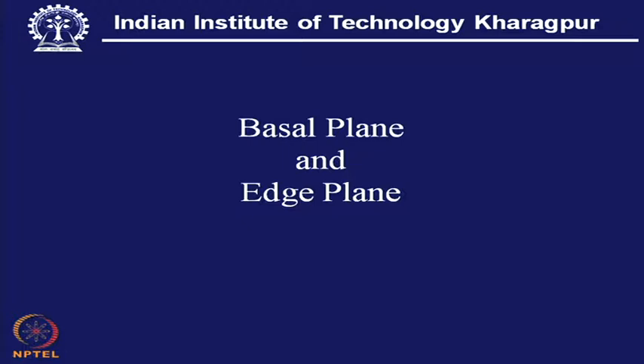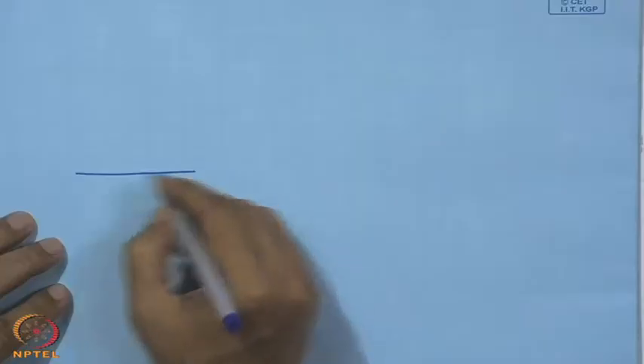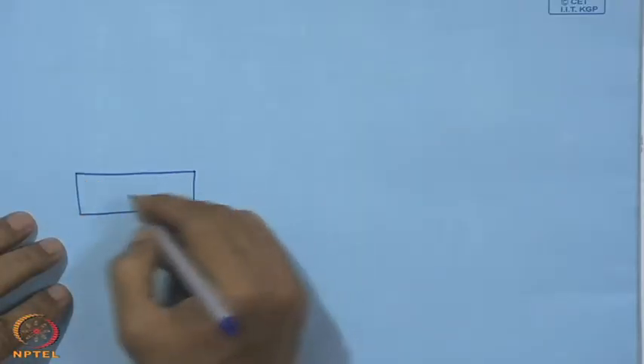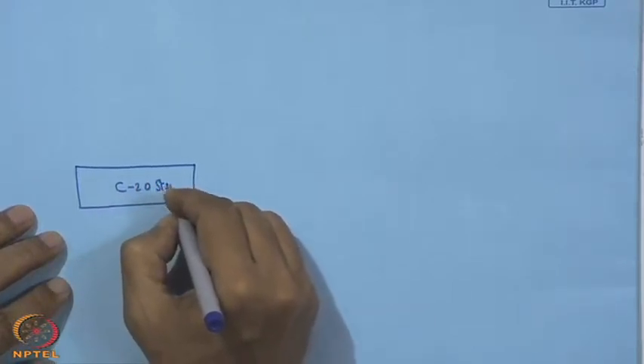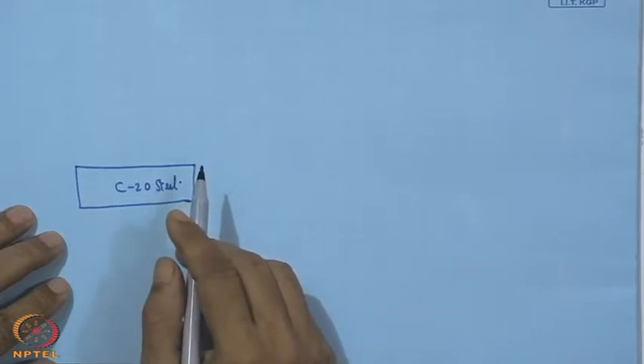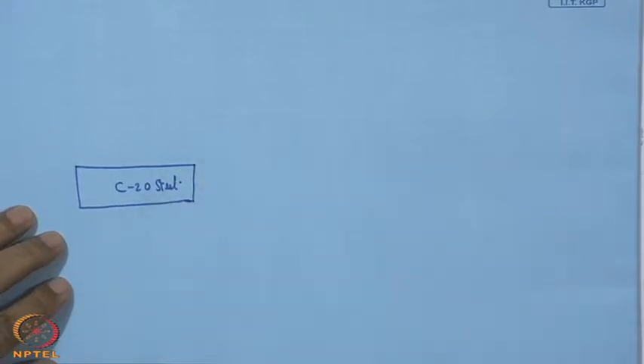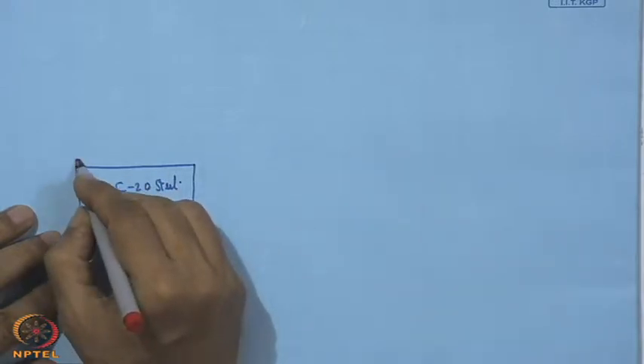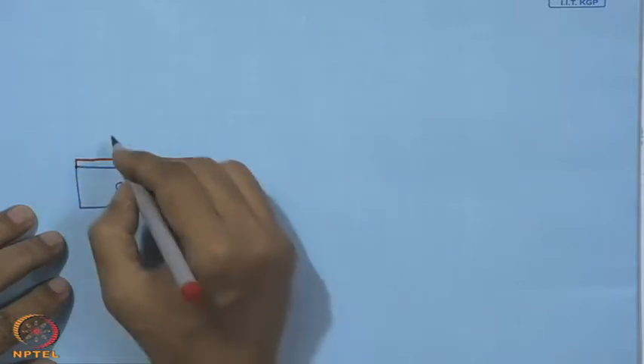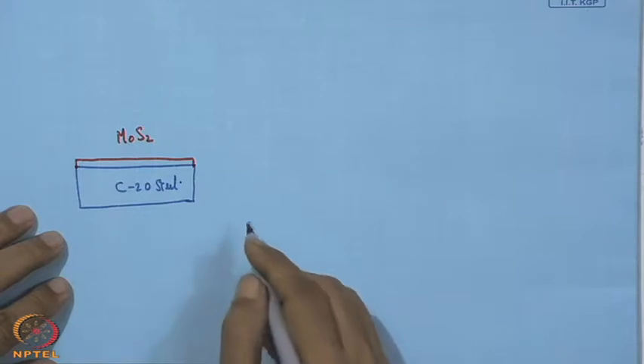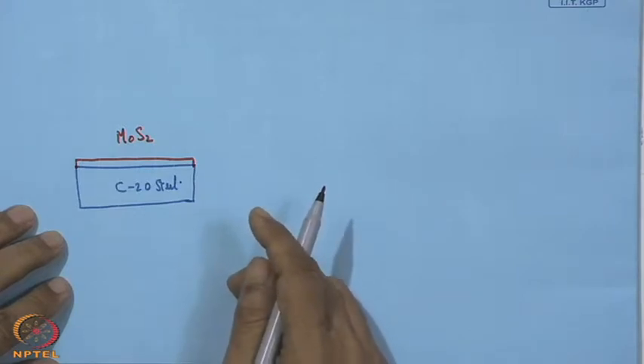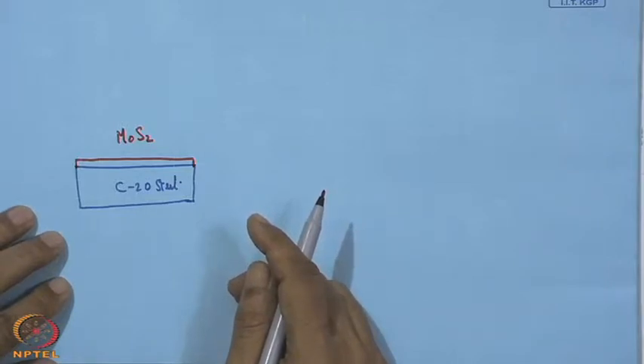Now, what we see in the actual field of working, say this is one substrate. It may be made of just a low carbon steel, C20 steel, and we like to deposit a coating of molybdenum disulfide over this. So, it is not just a coating of MoS2, but it will be MoS2 with the right orientation. And if we can't get this right orientation, we may not get a very good value of coefficient of friction or what we call super lubricious property. So, this is very important.